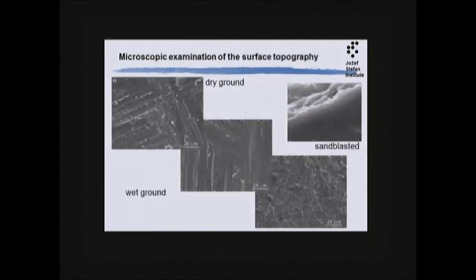And if we check the surface, you see the ground surface in any case was heavily damaged, in part plastically deformed. You won't be surprised to see sparks. It must be very high temperatures, and also this one, the sandblasted material, was also heavily damaged, perhaps less plastically deformed than that one. On the surface, it's perhaps not the transformed monoclinic, but it looks like it. So you get at least an impression. Perhaps one grain would be transformed in this material.